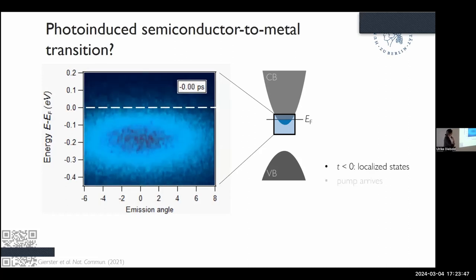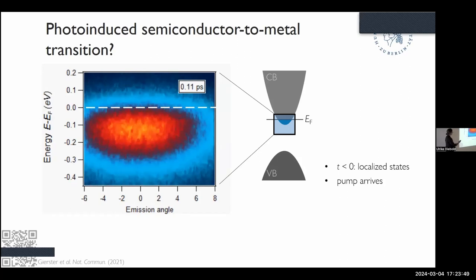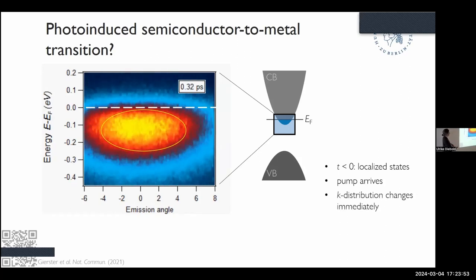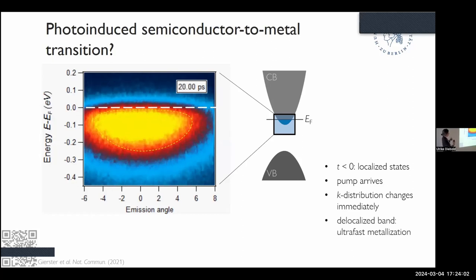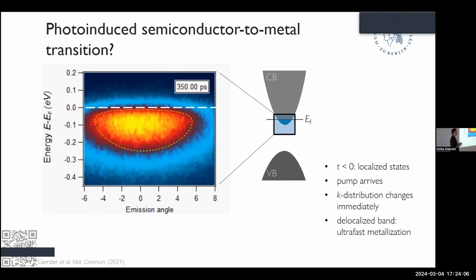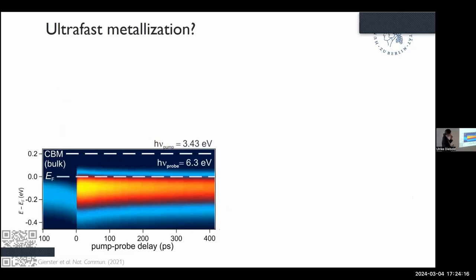Now at zero, you see the intensity suddenly rise significantly. And you see not only that the number of electrons below the Fermi energy has increased, but also the shape has changed. It has become kind of a smiley face. Yeah. And this is the delocalization of the electrons in the defect exciton state. Of course, one can analyze this also quantitatively. I will show you this in a moment.